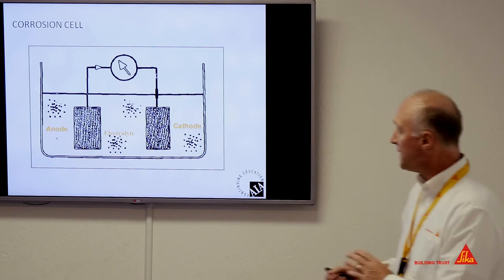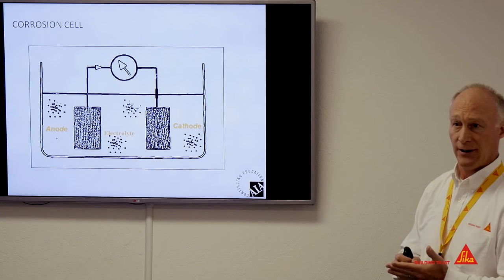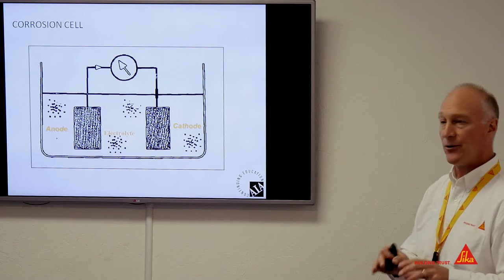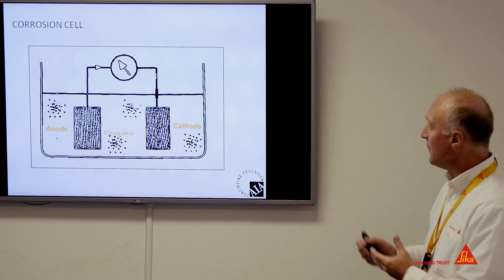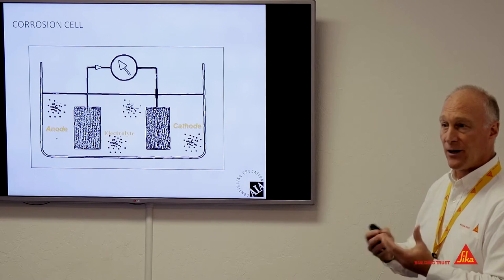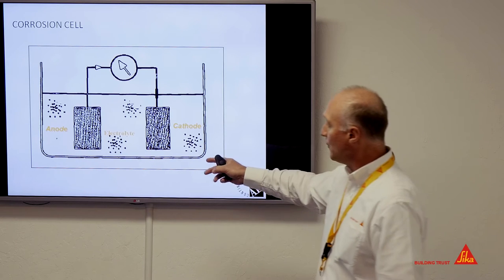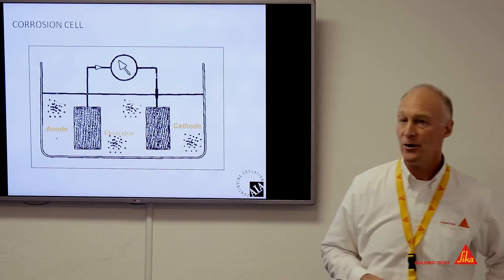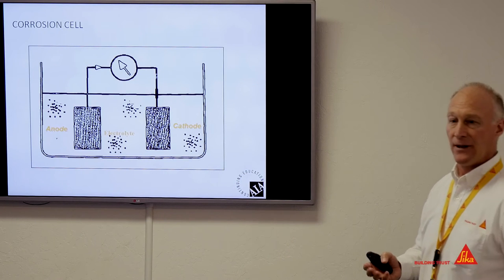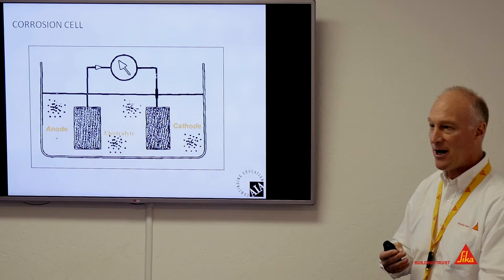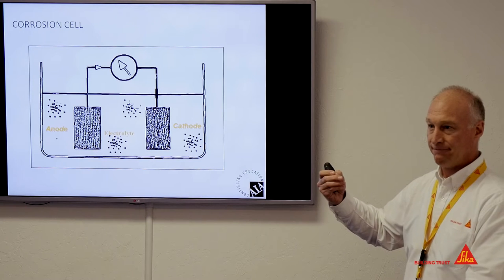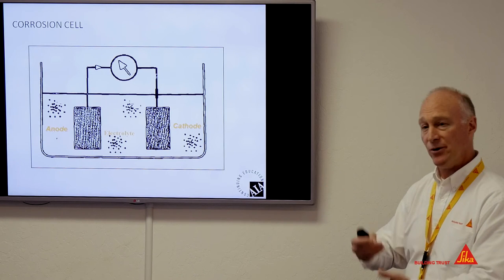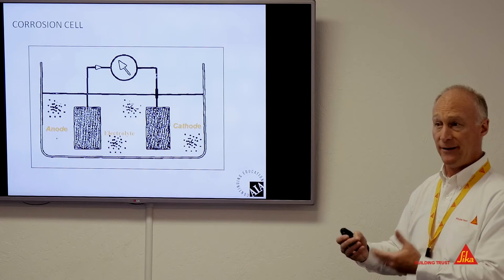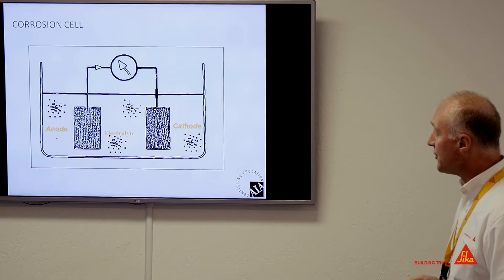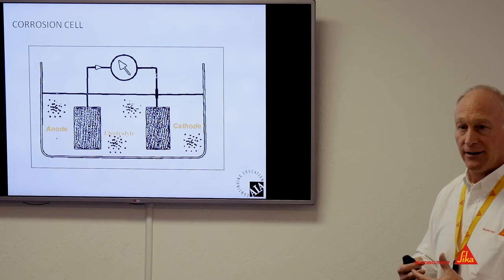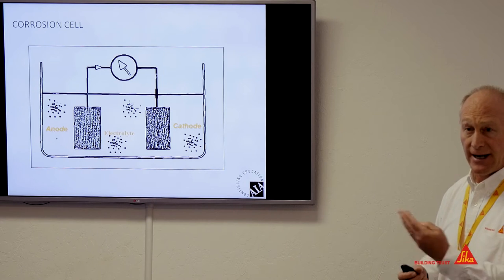Over time, basically all you need for corrosion is four things. I've mentioned a lot about chlorides and carbonation, but you don't necessarily need those. Those are more accelerators. You need what we call an anode and a cathode. Think of it almost like a battery, right? You need an electrolyte, which in our case is going to be concrete. In our industry, we refer to concrete as a hard sponge, right? It's always partially saturated. It's never 100% dry, and unless it's submerged, it's not 100% moisture. It's always somewhere in between. And as long as it's somewhere in between, you have a good electrolyte that will support corrosion. So if I have oxygen and moisture, which I do in a partially saturated concrete, those four things exist, so I can now have corrosion.